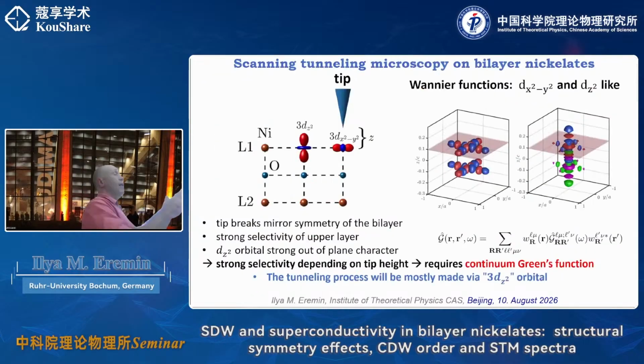Now let me come to the problem of the tunneling. If you come with a tip, then of course it never really hits the sample. Usually you try to avoid that. So the tip is always located at a certain distance with respect to the surface. And if you look at the extension of your Wannier orbitals, one has to keep in mind that in these models the oxygen is somehow unimportant, but that's not true, because we know that there is a hybridization with the oxygen. But in this case, you integrate out the oxygen states to make them a part of your dz square and dx square minus y square orbitals.